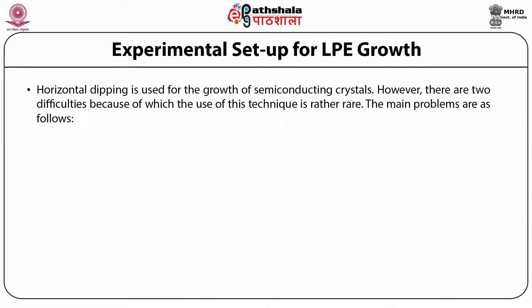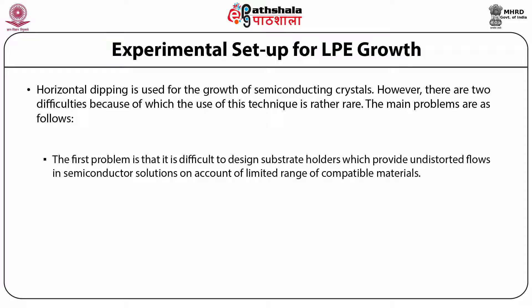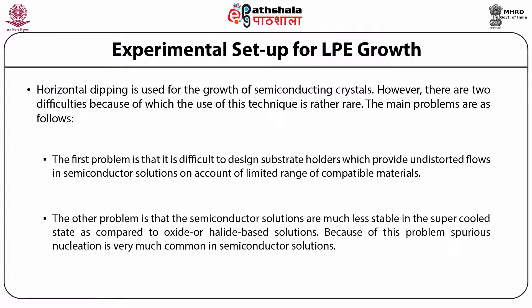Horizontal dipping is used for the growth of semiconductor crystals. However, there are two difficulties because of which its use is rather rare. First, it is difficult to design substrate holders which provide undistorted flows in semiconductor solutions, on account of the limited range of compatible materials. Second, semiconductor solutions are much less stable in the supercooled state as compared to oxide or halide-based solutions. Because of this problem, spurious nucleation is very common in semiconductor solutions.